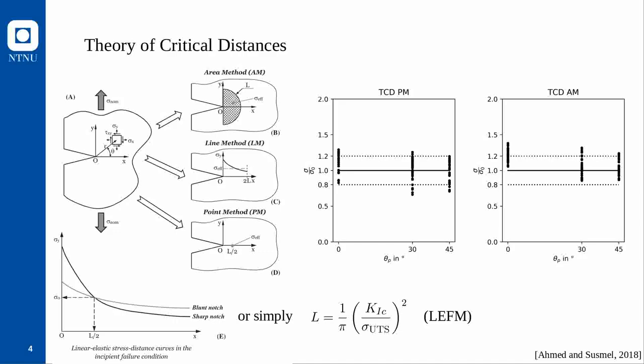The accuracy of the point method and the area method is shown here; both performed very well, with most scatter within the ±20% scatter band. The point method slightly exceeded that band on the non-conservative side — where a ratio below one is a non-conservative prediction — and the area method showed some conservative scatter. The line method was not performed because the required integration length to L would exceed the specimen dimensions.